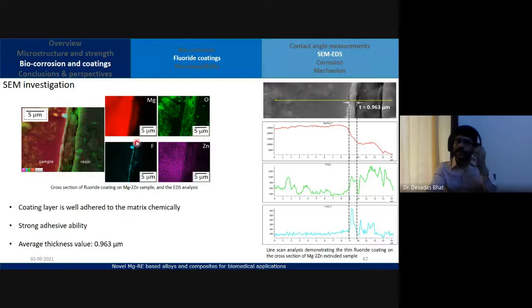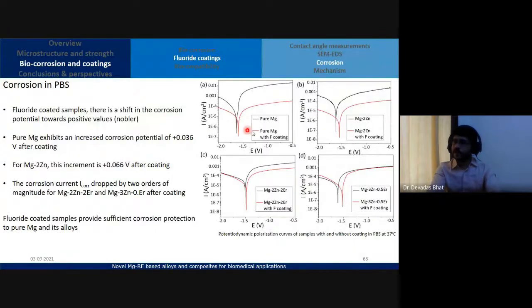And you could see here, the fluoride is more or less uniform along the surface, and because of the fluoride coating, we could see that the red ones are the coated ones. The black ones are the uncoated ones, and you can see there is a shift in the corrosion potential towards more positive or nobler values for the coated samples.